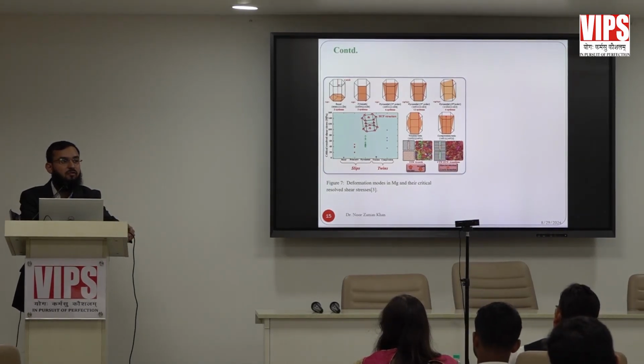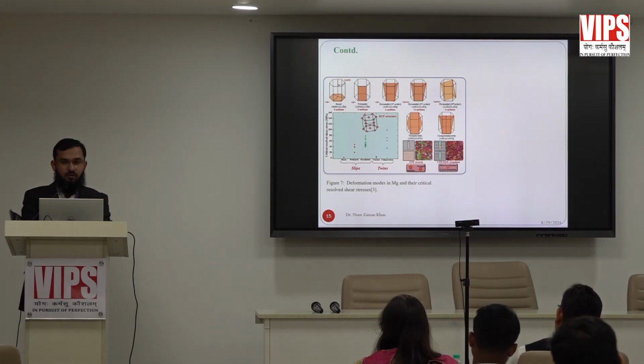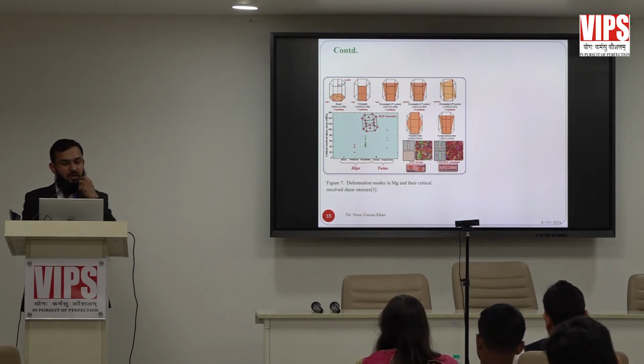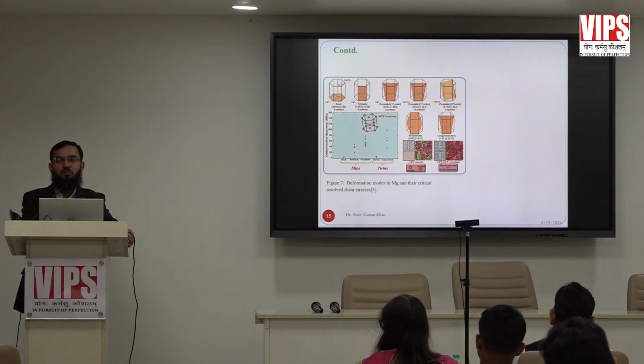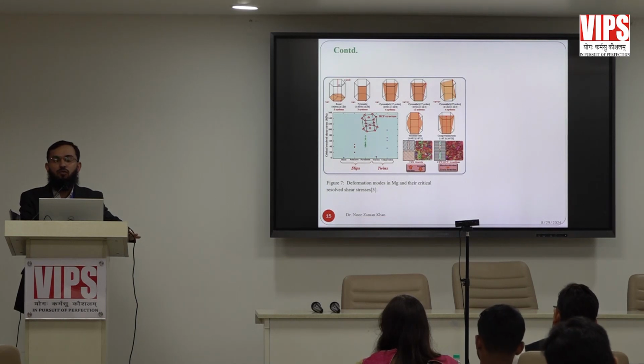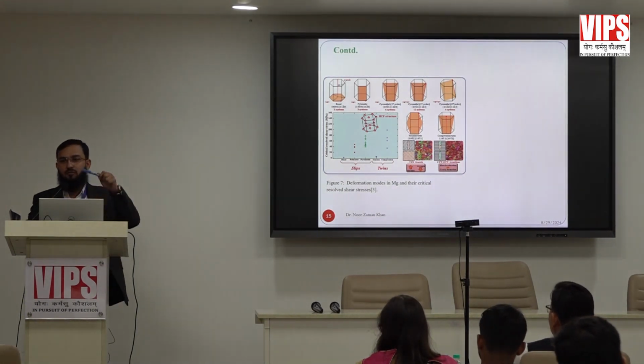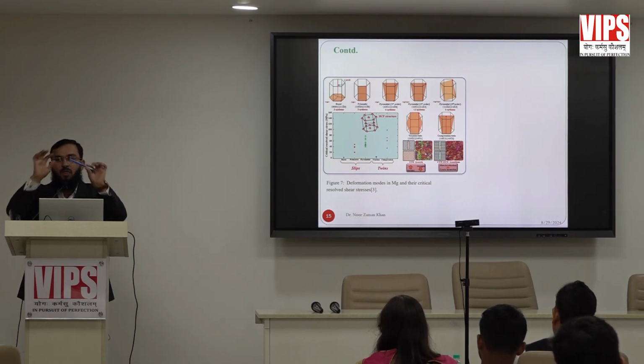This is nothing but the slip system of magnesium alloys. Very brief: if you want to deform any material, there are some slip systems. In magnesium, there are three different planes: basal plane, prismatic plane, and pyramidal plane. If you want to deform magnesium, the basal plane slip system is active at room temperature, but the other two slip systems are not active at room temperature. It means that if you are deforming magnesium at room temperature, only one slip system is active, due to which you cannot deform it completely. It will lead to formation of micro cracks. Suppose you have a pen made of magnesium, if you want to bend it, it will lead to the formation of some micro cracks.